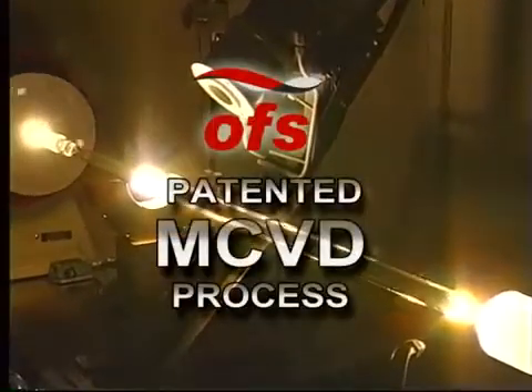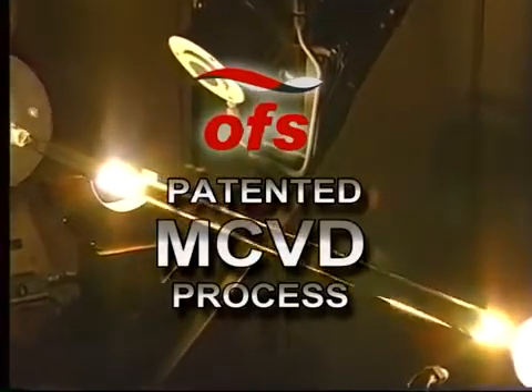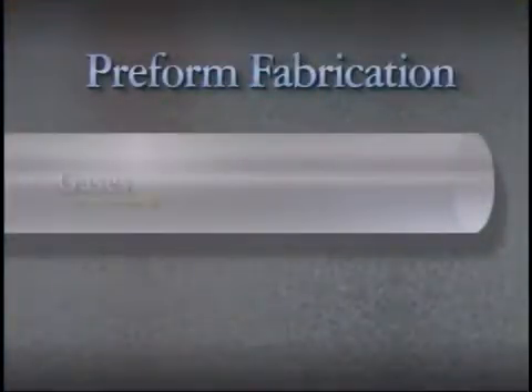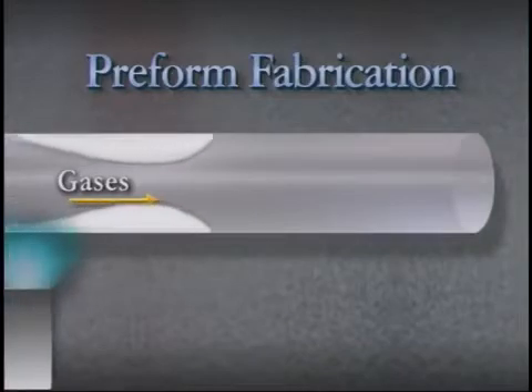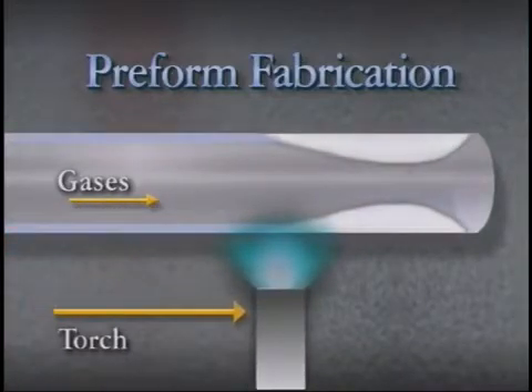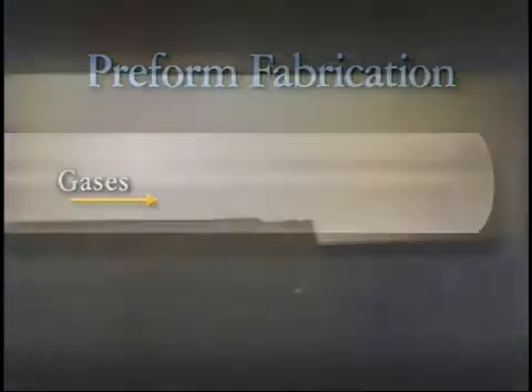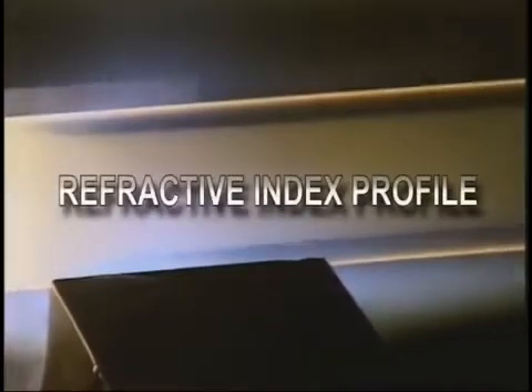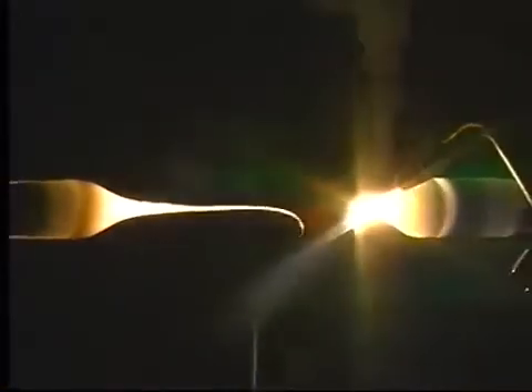In our patented modified chemical vapor deposition process, often referred to as MCVD, ultra-pure chemicals are introduced into a synthetic silica glass tube. As a special torch moves along the rotating tube, white soot is deposited on the inner wall. The soot is then further heated and fused into a thin layer of pure transparent glass. Many of these layers are combined to form the waveguide region of the fiber. Layer by layer, the MCVD process creates the precise waveguide profile, also known as the refractive index profile, that's necessary for today's high-performance laser-based communication systems.